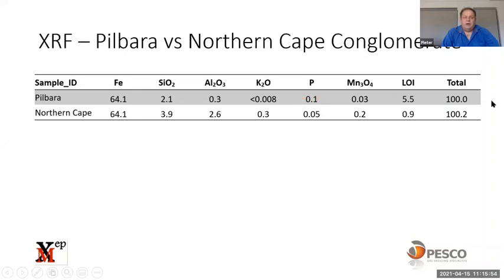A much lower silica versus a typical Northern Cape of 4%. Alumina, Northern Cape is normally between 1% and 2%. Phosphorus, very low, 0.3%. The potassium in the Northern Cape is normally between 0.1% and 0.3%. Here we see the potassium of 0.008. That is quite significant, and I think that's important to take into account when you look at your minerals, what is the rest of your contaminants inside a sample.